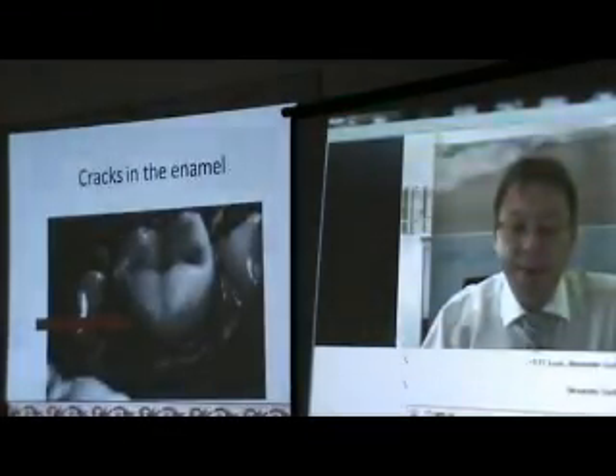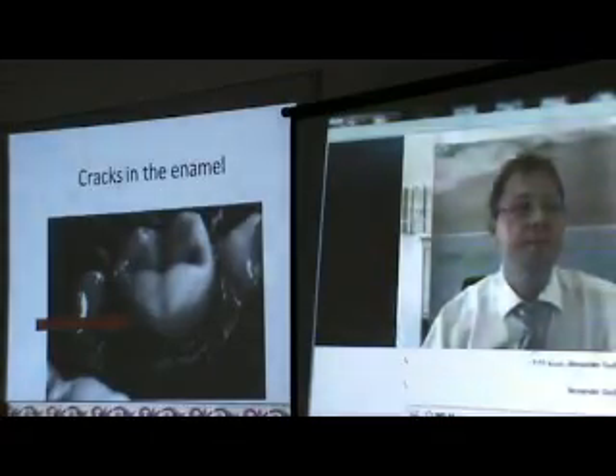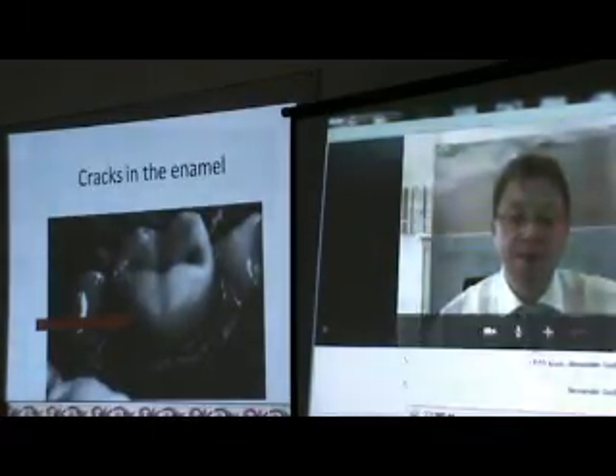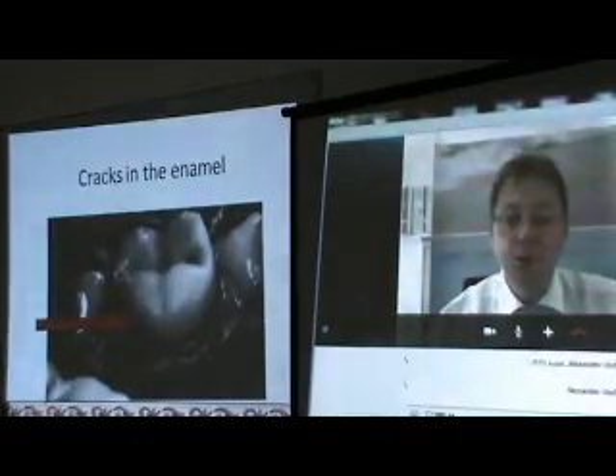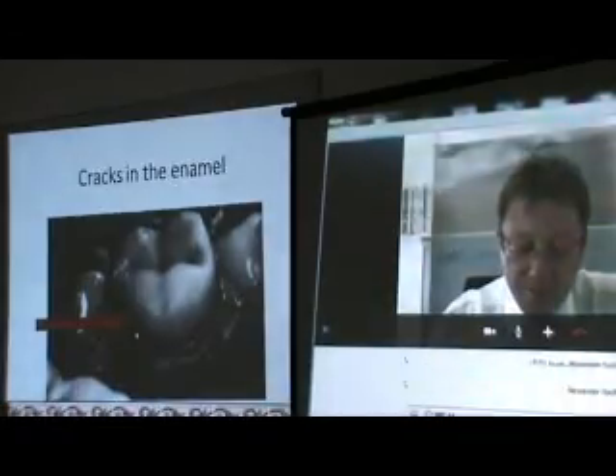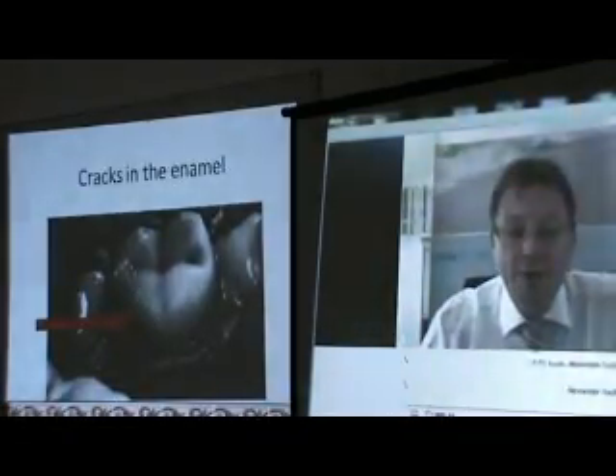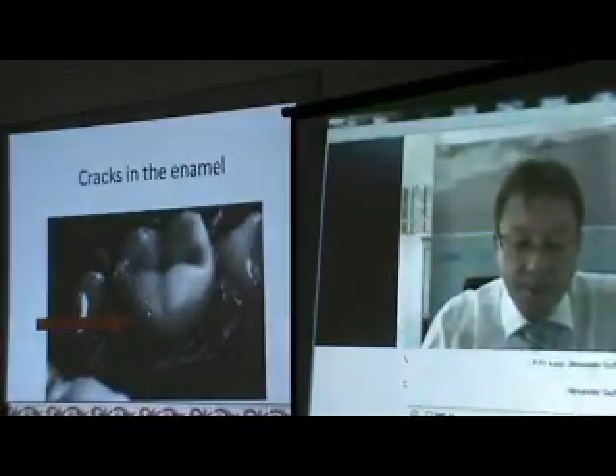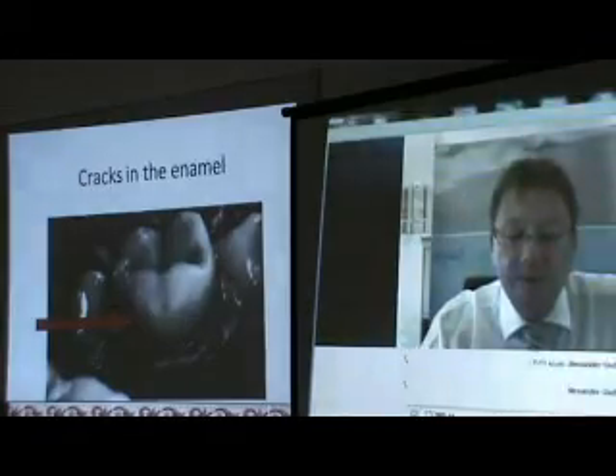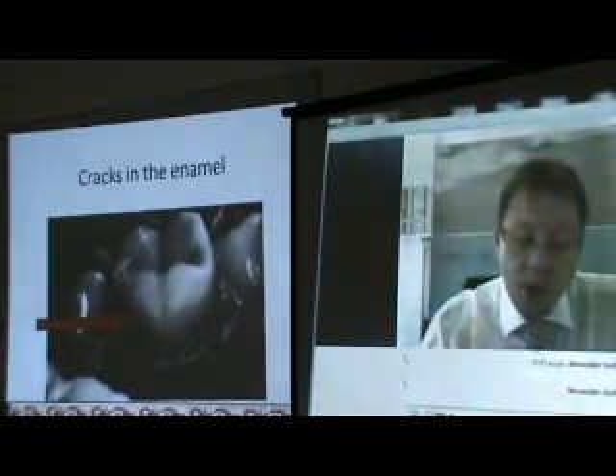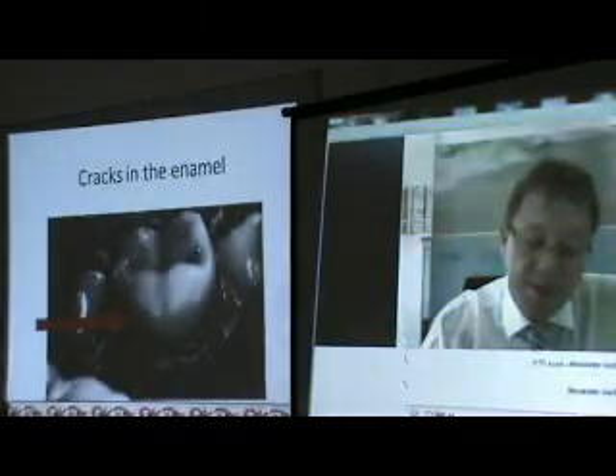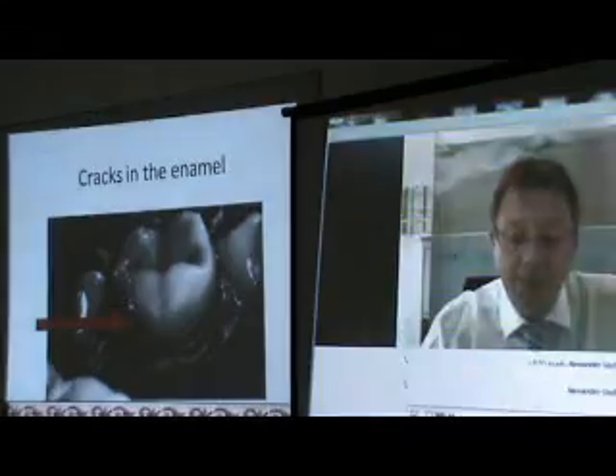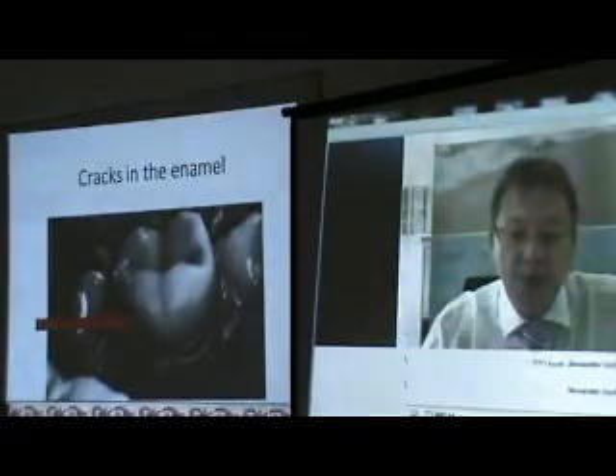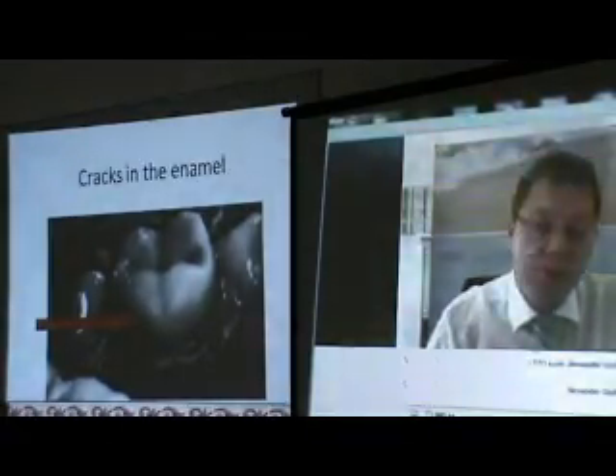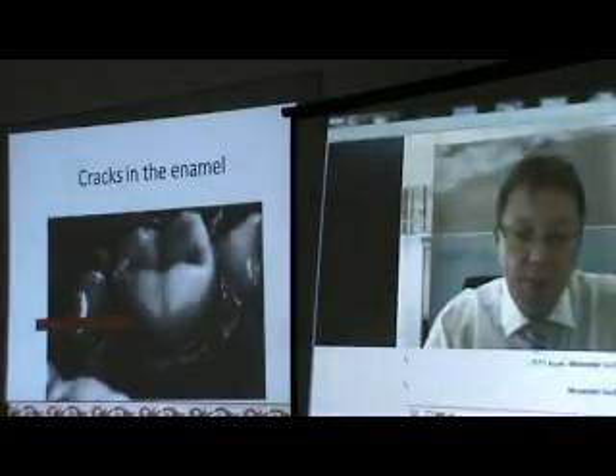Slide 32 was taken by the University of Zurich in Switzerland. And here, actually, you see these micro cracks which are due to the shrinkage stress of a composite. Here you have an extreme case. You see on the right side, on the right part of the tooth, it is all the composite restoration. Only the small part on the left, where you see the cracks, where you have the flash, this is the natural enamel. Now, this picture was taken 30 minutes only after the restoration was done. 30 minutes before this picture was taken, there were no cracks on the natural enamel.